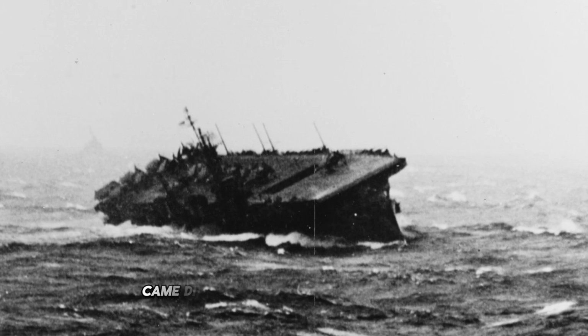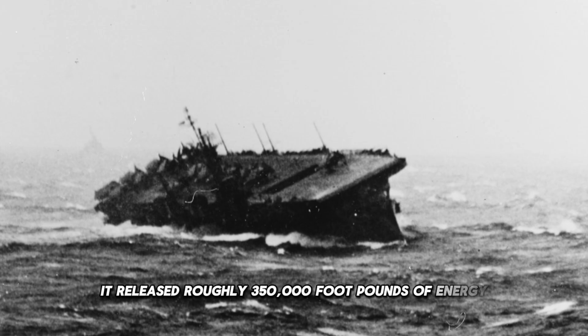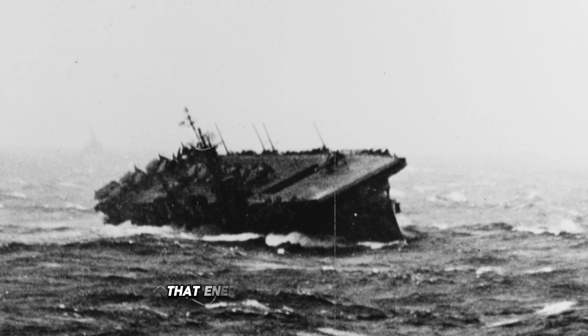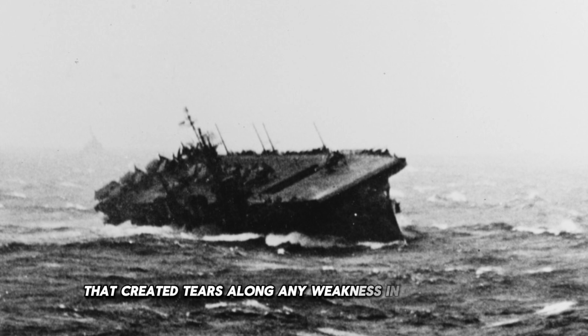This specification came directly from weight calculations. Thicker plating would have made the LST too heavy to achieve its required speed of 12 knots and would have reduced cargo capacity. The 3/8-inch plate was adequate for resisting small arms fire and shell fragments. It was completely inadequate for mine blast effects. When a 75-pound Teller mine detonated, it released roughly 350,000 foot-pounds of energy in a fraction of a second. That energy had to go somewhere. With a flat hull offering no deflection, the blast wave compressed the steel plating, then released it in a rebound effect that created tears along any weakness in the structure.